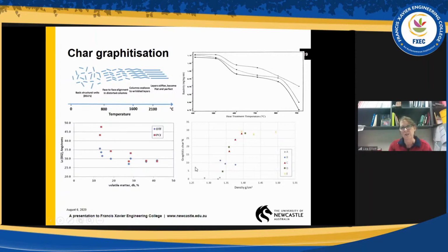The other way to measure it is to use the reactivity of the material as a measure itself. What we've done in this one is to measure how much of the coal disappears at each reaction temperature. So at lower reaction temperatures, chars that are graphitic in nature are not going to react, whereas chars that are non-graphitic in nature will require much higher temperatures to react. So we used a TGA and changed the reaction temperature progressively and measured those changes, and were able to show that the graphitic nature of the char was a function of the density of the starting material.